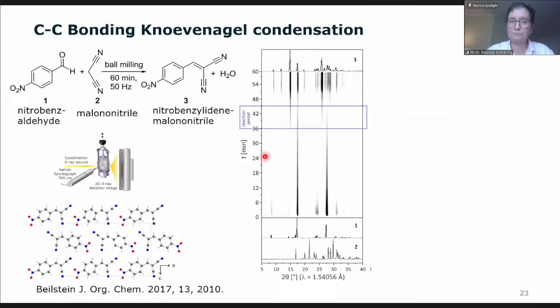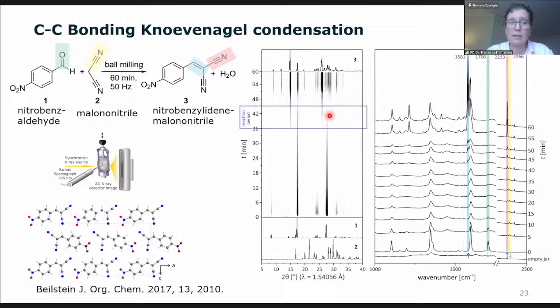And here you see again the X-ray diffraction data. We only see the aldehyde because malononitrile is a liquid, or melts at an early stage in the reaction. And you see we need around 50 minutes for a full conversion. So the X-ray data looks a bit boring, but in Raman you can clearly see that we are losing the contribution of the aldehyde group. During the process, the CC bond is formed here in blue, and we see the shift of our nitrile group from starting material to product.